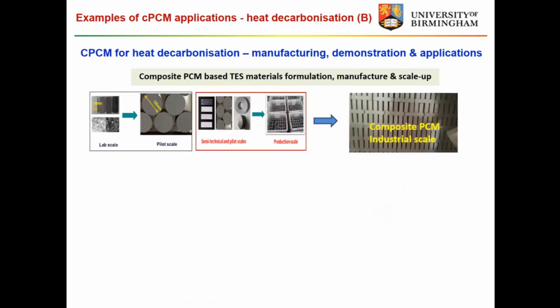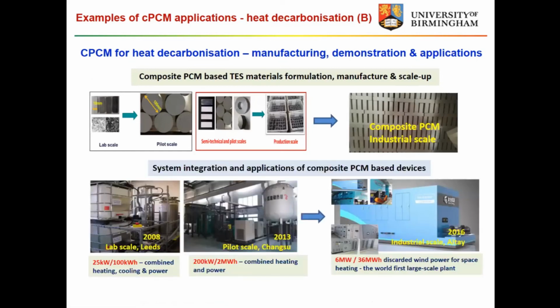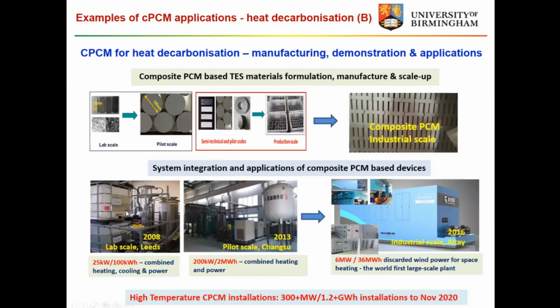Through the last about 15 years of development, we have managed to make the materials at hundreds of tons per day capacity, and we have done quite a bit of demonstration, from very small scale, about 25 kilowatts, 100 kilowatt hours, to medium scale, which is 200 kilowatts, 200 megawatt hours, and to the world's first large-scale composite phase change material application near the Kazakhstan and Xinjiang border, which is 6 megawatts, 36 megawatt hours, and uses discarded wind power for space heating. In short summary, high temperature composite phase change material installations total more than 300 megawatts and over 1.2 gigawatt hours as of last year.